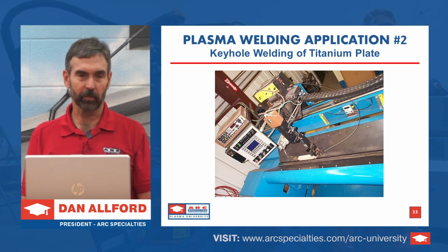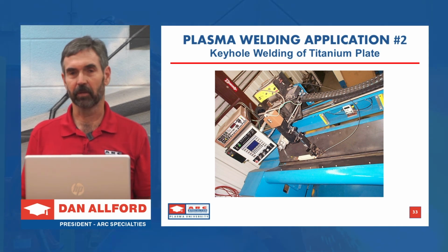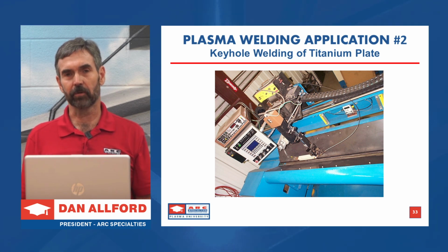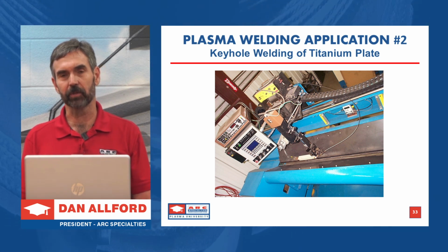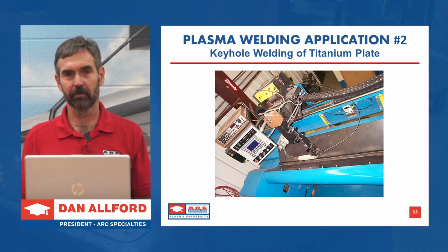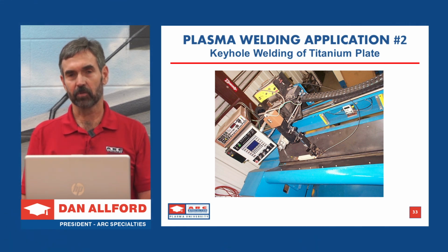But we have to cut all the way through the part in order to refuse it behind the torch. And so by increasing that plasma flow rate, we'll punch all the way through the part and create a keyhole, as the name would imply. And it goes all the way through the part.